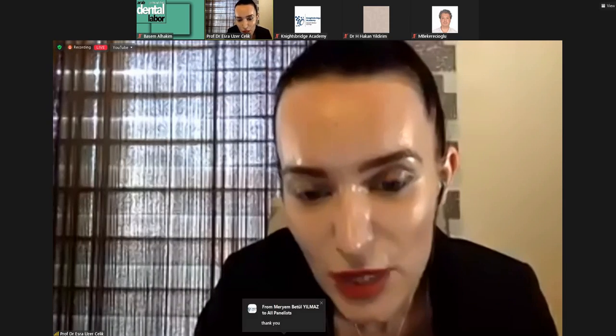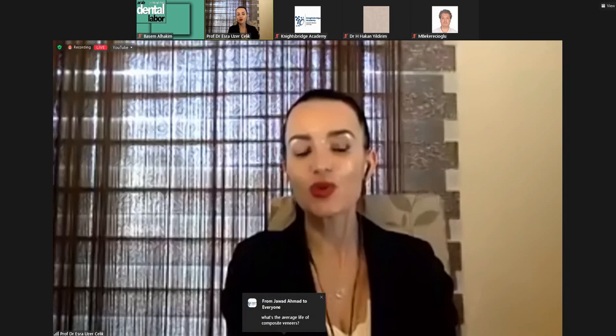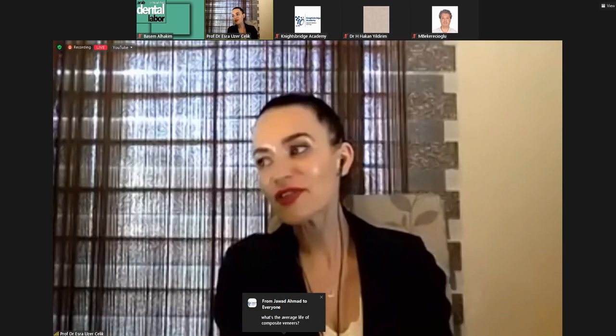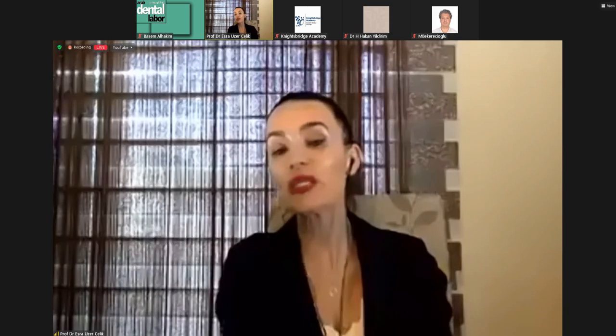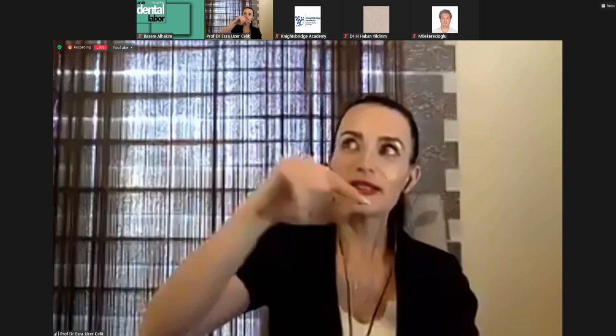And for Zainalo: do you use a composite sealer such as PermaSeal by Ultradent after polishing? This is also a very good question, because PermaSeal is a very good material, and yes, it can be used, but not in all restorations, because we generally prefer not to use any resin-based material on the surface. But if there's a gap, or if there are bubbles in your composite resin after finishing, in that case, you can use PermaSeal. PermaSeal is a very good glaze material. And we use glaze materials if there are small gaps or small white areas near the margin or on the surface. We don't use optical glaze materials or PermaSeal for shining or lustering the surface. Generally, classical polishing is enough for that aim.